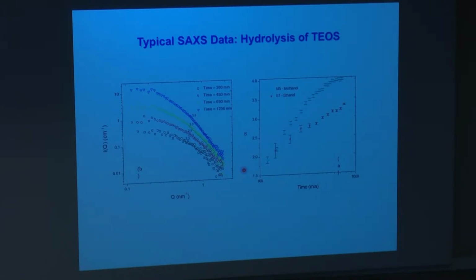So the cryo-TEM particle was kind of a low-density particle, and sure enough, X-ray scattering also showed that indeed the particle is a low-density particle that densified over time.